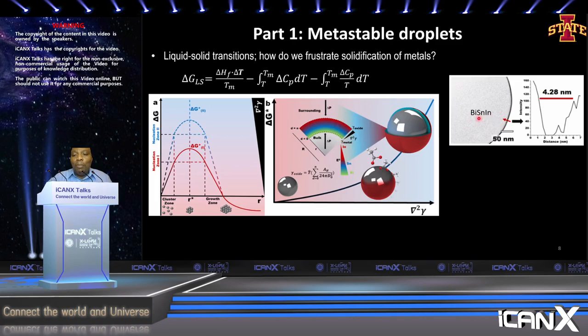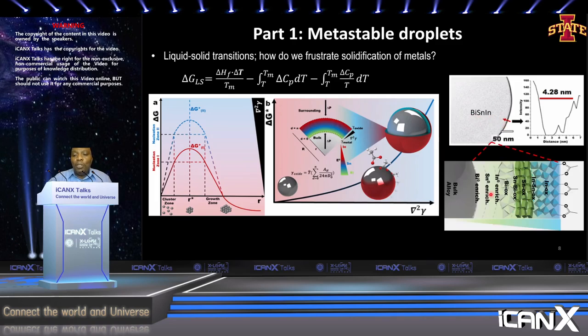And since it has 3 components, we asked ourselves, how is the distribution going to look like? And the distribution looks something like this. The most reactive component ends up being all the way on the surface, and we stabilize this using an organic ligand so that the oxide remains very smooth and very polished, so it doesn't have any kinks that will nucleate the material in the core heterogeneously. And then there is a gradient from the most reactive indium to the tin, and then bismuth ends up being at the interface between the metal itself and the oxide shell.